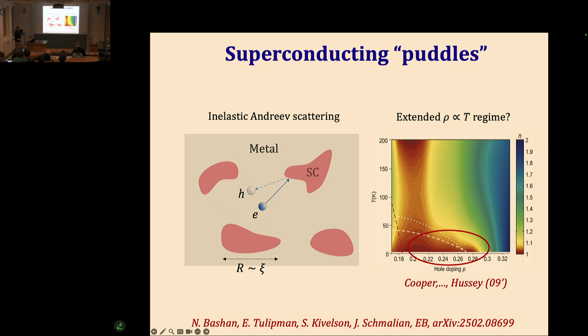So this is a somewhat unconventional argument. For a long time, people have been arguing that this high temperature behavior sort of extends all the way down to low temperature, therefore the mechanism is the same. Now, if you look very carefully in the data, in LSCO, there is actually a subtle crossover somewhere. The slope is not exactly constant all the way down to low temperature. In other cuprates, in YBCO, for instance, there is a very similar high temperature linear T resistivity, but if you just try to extrapolate, it extrapolates to a negative value, which means that it can't possibly go all the way down to zero temperature without a change of slope. So I want to argue these are different mechanisms. The change of slope here is not enormous, so that's not completely clear.